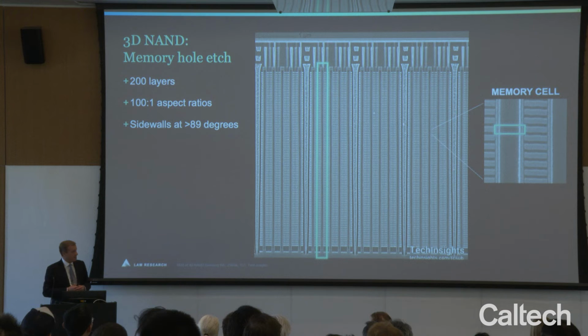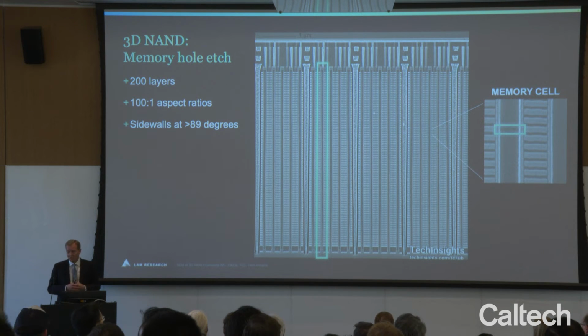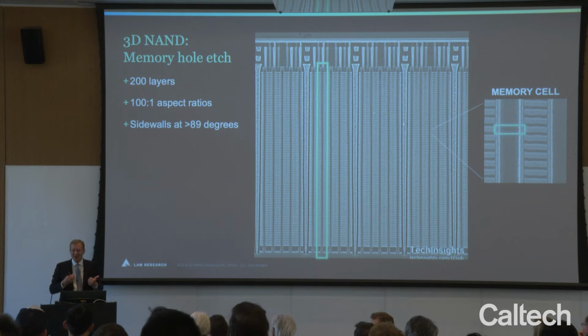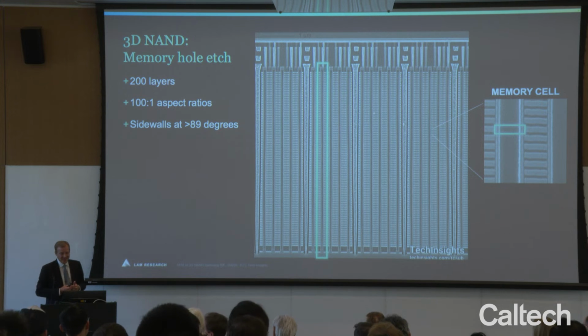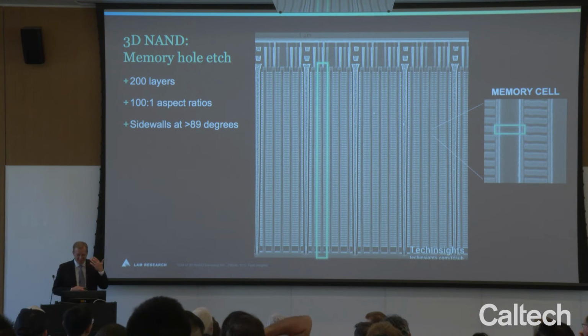The challenge with 3D NAND is that we actually have to etch these types of holes through 200 plus alternating layers of oxide and nitride. The aspect ratio for the hole that has to be etched is approaching 100 to 1. It has to be 89 degrees to vertical. And if that's not already enough, there was a comment about the hero results. We have to do this 1 trillion times on every 300 millimeter wafer. And every month, there are 1.5 million wafers produced worldwide. It's a lot of holes we have to drill. And so it creates a manufacturing challenge.